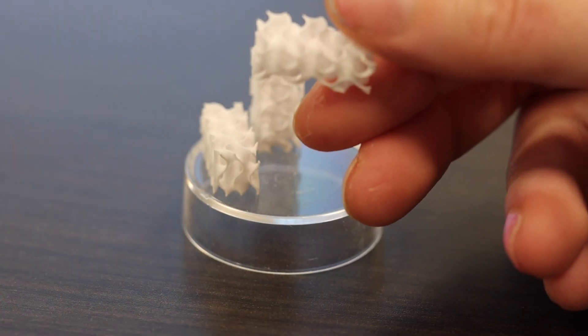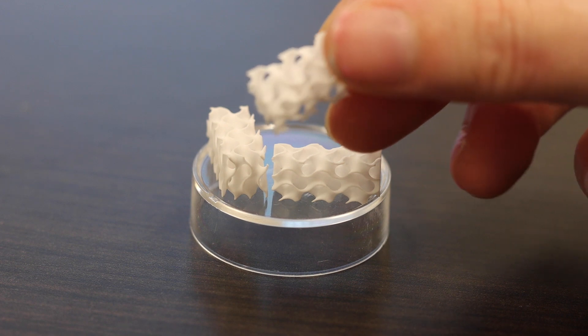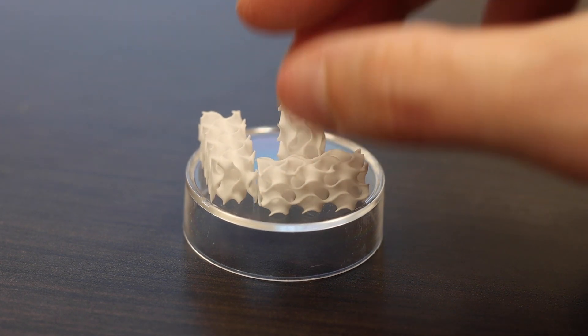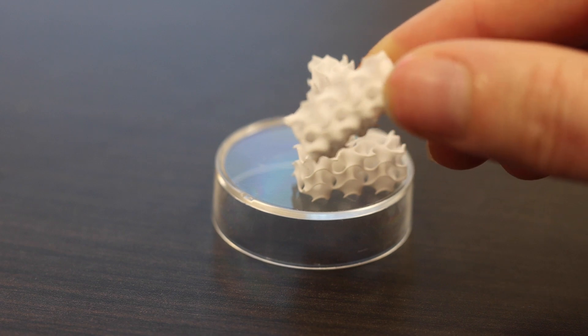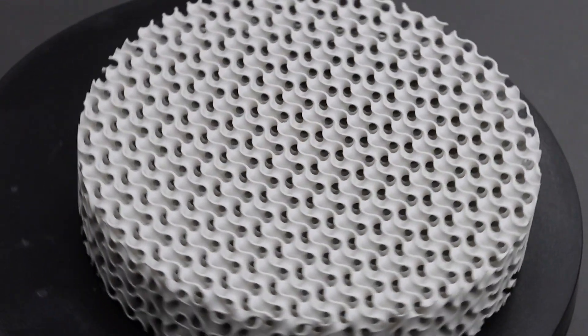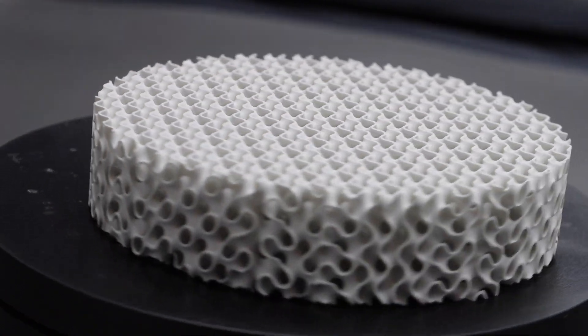The samples you're looking at here are some waveguide test samples that allow us to characterize the effective dielectric constant of this alumina material. We leverage this approach to help our customers use effective media design to create a wide range of effective dielectric constants. With a bulk dielectric constant of 8 DK, we have a much expanded total effective DK range. The wall thickness of this material can go down as small as 250 microns, which realizes an effective dielectric constant of about 1.6 DK on the low end. Our waveguide test method is currently being validated using a free-space test method — using a focused beam to characterize transmission and reflection of this test sample to confirm measurement accuracy.